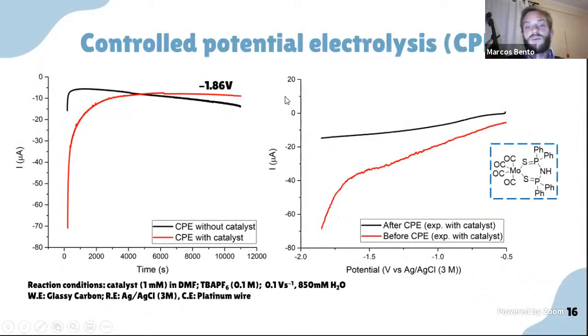In order to quantify and detect the different products of this conversion, we did some controlled potential electrolysis experiments, and through the analysis of the current-time graph, we can see a decrease in the current, which indicates catalyst degradation. This can be also confirmed through the difference in the linear voltammograms before and after the electrolysis experiment.